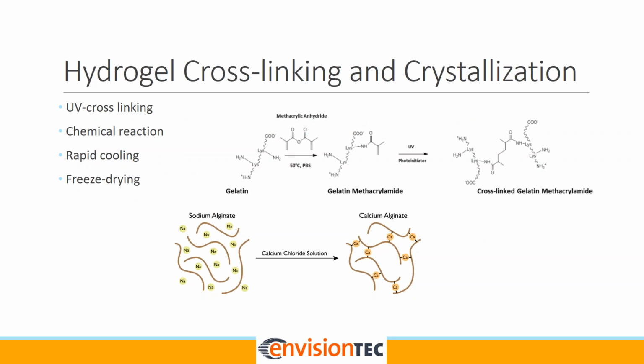With hydrogels, you can, again, use UV cross-linking. It's not important to know the specific compounds, of course, but you can see the general course of the reaction is you have a base chain, apply some UV light that acts on some sort of chemical group, and it binds together. The chemical reaction is a little bit tougher to visualize, so I have the diagram below. You create some sort of solution, including your chain of interest, in this case alginate. Sodium will disassociate from the alginate when you put it in water, and then by incorporating calcium chloride, since calcium chloride can bond to two alginate chains instead of sodium binding to one,